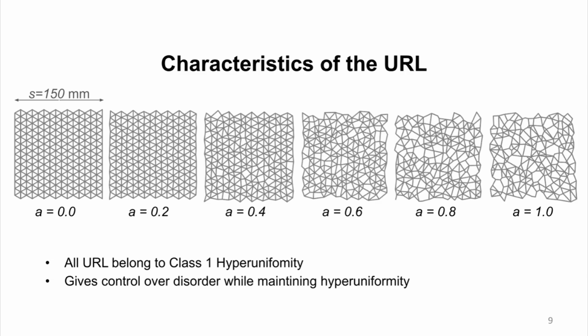The URLs of all the different perturbation strengths are known to belong to class 1 hyperuniformity, and the parameter A gives us independent control over the amount of disorder we have in the system, and the specific different strengths of disorder I use are 0, 0.2, 0.4, 0.6, 0.8 and 1. These are again fractions of the original ordered interpoint spacing between the original point cloud that I start with before perturbation, and those are the characteristics I just described.